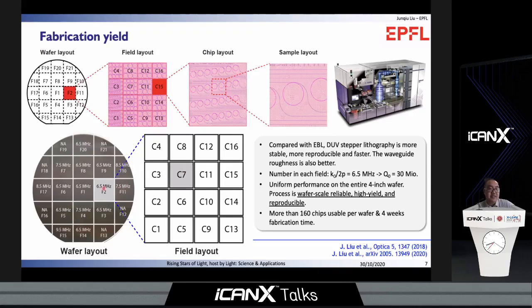As you can see here, we can achieve 6.5 megahertz linewidth in nearly all the exposure fields. This means that our process is wafer scale reliable, high yield, and reproducible. We can generate more than 160 usable chips per wafer, and the fabrication time is about 4 weeks.